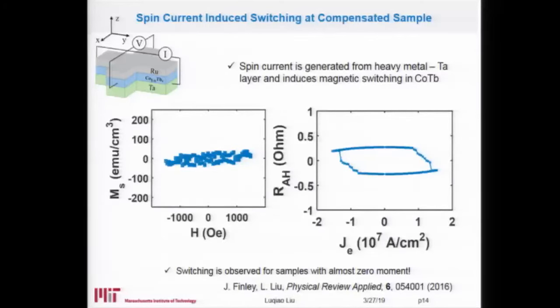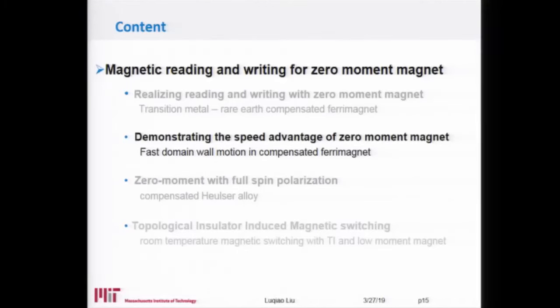So far, we show that by utilizing such a zero moment magnet, cobalt-terbium, we can realize both magnetic reading through the anomalous Hall resistance, as well as magnetic writing through the applied charge current. Okay, so this is the first step, because we remember our goal is to realize fast magnetic memory. And here, at least, we show that we can read and write information into those magnetic materials. The next step is to show that there is some speed advantage associated with those zero moment magnets.